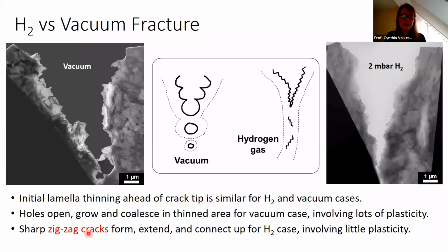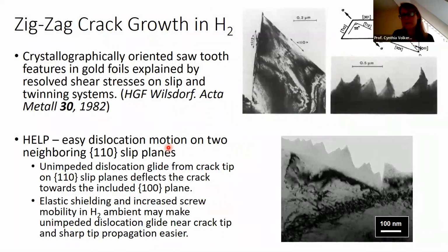So the question we have now is, why are zigzag cracks forming? What are the possible mechanisms for that? And why is that promoted by hydrogen and not observed in the vacuum case? There is a study out there on gold without any hydrogen showing zigzag structures. It's not something that we found to be very common in the literature. In this study, they explain this by arguing that these features are formed by either shearing or twinning, and that they're activated by whichever has the maximum resolved shear stress. So that's the simple picture: if the applied stress activates dislocations for shearing or twinning, then that's what will happen, and the deformation will then result in these zigzag surfaces.